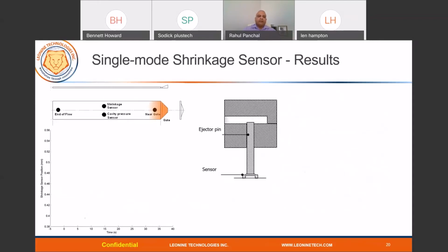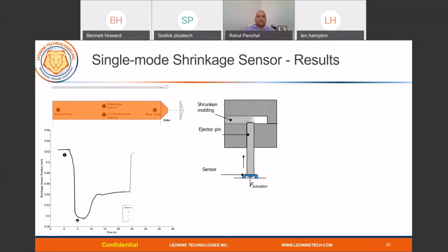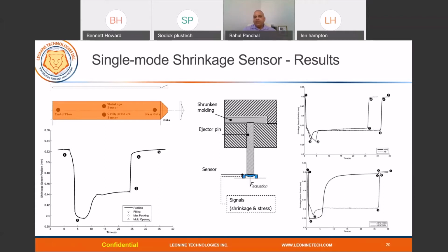So look at that, you can see the sensor location: now the fill stage. Now the sensor is fully activated. Now the part is cooling down. Once it cools down, it will move upward while still remaining in contact with the plastic part and without deforming the plastic part. And this is a typical profile for the 1.5 millimeter thickness, and this is for the HIPS, for different thicknesses.